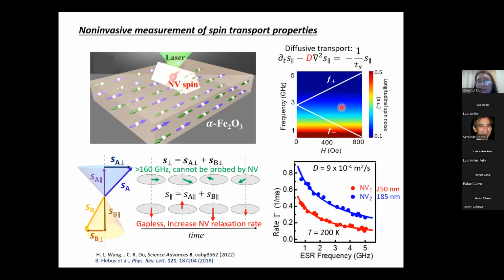In our measurement, we can vary the external magnetic field. This allows us to change the NV electron spin resonance frequency, so we can use that to probe the frequency dependence of the longitudinal spin noise. Here we can see our measurement result shows that the NV relaxation rate indeed changes with the NV electron spin resonance frequency in the expected way: it decreases with increasing frequency. By fitting this frequency-dependent relaxation rate, we can extract the spin diffusion constant, which is about 9 × 10⁻⁴ meters squared per second at 200 Kelvin for the alpha iron oxide.